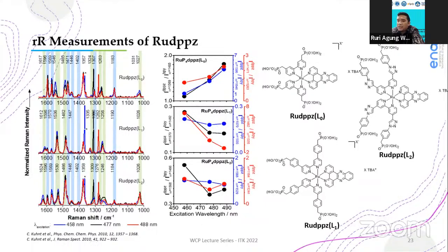And this result indicates that the additional linkers for ruthenium L1 and ruthenium L2 lower the PP associated LUMO energy. So that's why the charge density shifts toward the anchoring ligands here. So the charge density is shifted from the DPPZ toward the PP ligands if we add additional linkers. This is of course not expected for p-type dye-sensitized solar cells, as I introduced in the beginning, since the charge density at the PP ligand will screen the hole injection.